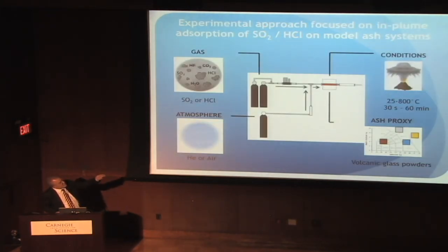So the last stage of the work that I want to show you about here is that we're developing a reaction chamber now for looking at the reaction of ash with the co-erupted gas. Sounds crazy. It was all together in one rock. Bang, it got fragmented. But of course, as soon as you move temperature and pressure, equilibrium shifts, the ash particles, still hot, are now being exposed to these nasty aggressive gases which they used to have inside of them. And they start to eat their way into the surfaces of the ash particles. And we believe that up to half of the sulfur which comes out in this cocktail can actually be lodged into the surface through diffusion and through precipitation of crystal phases and never gets out of the volcanic deposit. Just to be controversial these days, we call it sulfur sequestration in volcanic eruptions. Literally, and got it published.